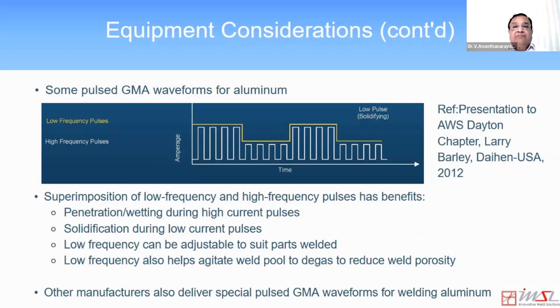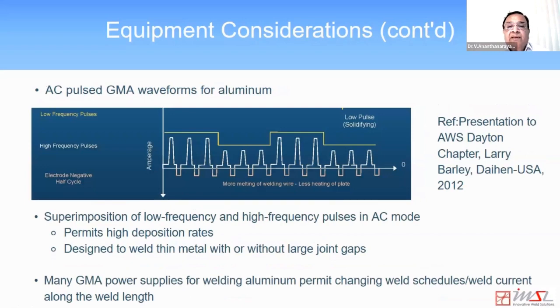And this kind of imposition of low current and high current pulses is also done in the AC mode. It permits high deposition rates and is designed to weld thin metal with or without large joint gaps. Again, my apologies for this error here. It's not low frequency, it is low amplitude or low current. Many gas metal arc welding power supplies for aluminum permit changing weld schedules and weld current along the length as well.